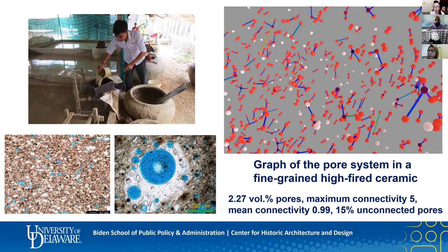Okay, so the first is, how do you tell things that are just surface abrasion, not a specific pore? You can exclude the very surface from your region of interest for analysis. You're actually only analyzing the ceramic body itself. That would be one way to do that if you have a lot of surface abrasion, because those would usually be dips into the surface. So you can exclude those when you construct your region of analysis for image analysis and segmentation.